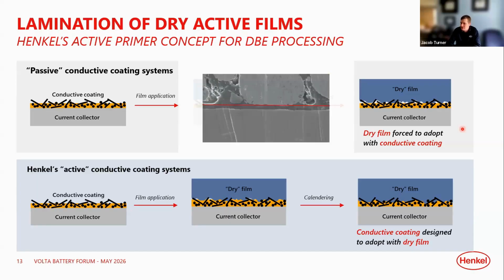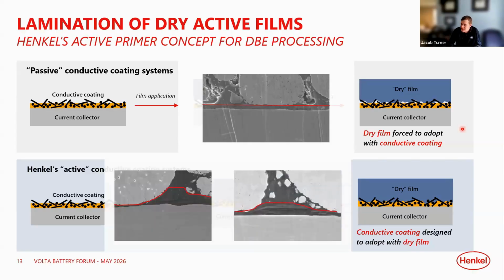We can actually see this under a microscope after lamination, where if we use a passive coating system or a reference that's out there, you'll see this very defined interface between the conductive coating system and that of the active material. There's often a lot of void spaces near that point where there's not full contact across that. When we go to our active system, you'll see that this interface gets a little more blended. We typically don't see voids at this interface, and we get a really strong adhesive performance between the conductive coating and these dry films.